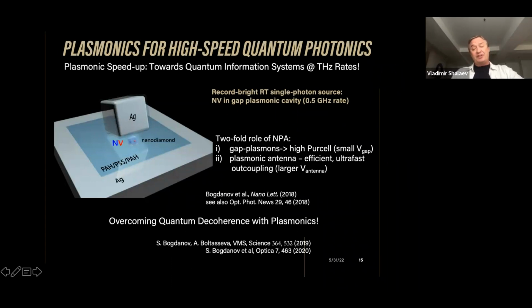So what you need from your nano-antenna is actually two functions to accomplish. You would like to have the gap as small as possible. The smaller the gap, the smaller the volume, the stronger the Purcell enhancement, the stronger increase in light-matter coupling. But the gap should be small, while the antenna itself should not be too small, because you need to outcouple these single photons. And the rate with which you outcouple depends on the volume of your antenna. So it turns out that the optimal size is in the range of, let's say, 80, 100 nanometers.